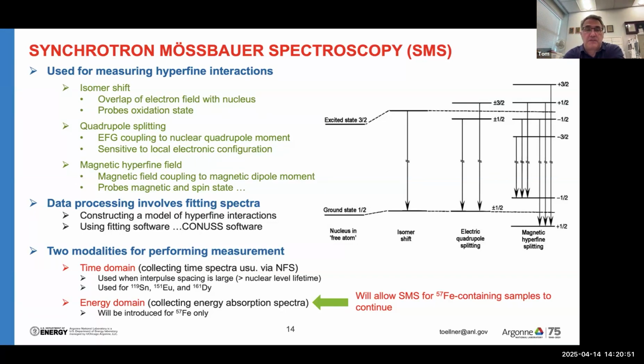The spectra themselves can be done in two different ways. One is in a time domain. This is usually done in a forward scattering geometry, but one can also do it by Bragg diffracting from a crystal that contains the resonant isotope. Generally, nuclear forward scattering is preferred because you do not need high quality single crystals for this. You can do any variety of samples as long as they're solids.